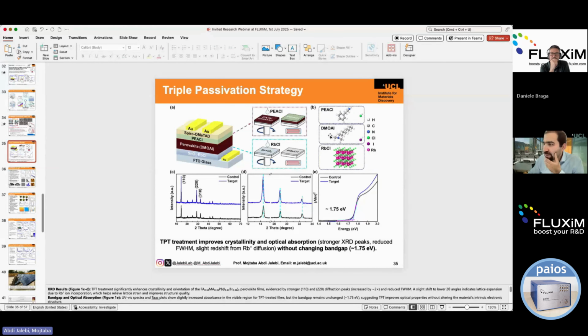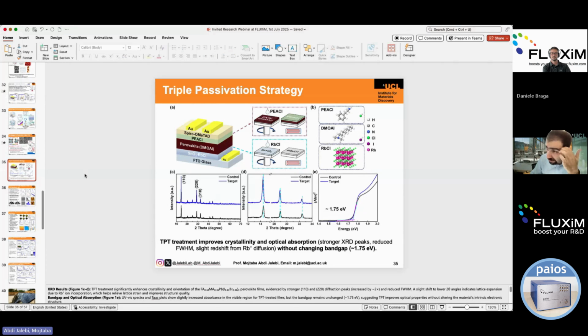Oh, sure, of course. Let me just make it a little bit larger for you. So yes, we are using these three different molecules for three different reasons. So the first one is PEACl, which we are using at the interface of the electron transport layer with perovskite. One of the reasons, as you have heard about the inclusion of chloride into the perovskite, is that normally chloride or halide can help you to make a better perovskite in terms of the growth mechanism. And for the large bandgap perovskite, this is a huge problem, how you can form it homogeneously and without any pinholes, etc. And one of the functions of this rubidium chloride at this interface is helping with the growth of the perovskite.